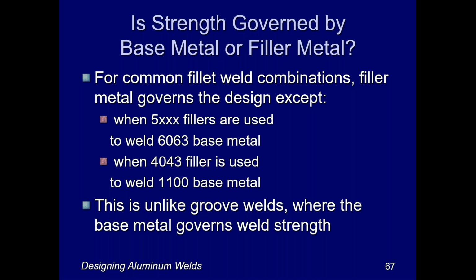And what that means is that you need to make the weld length appropriately long for the base metal. So when you have a case where the filler metal governs the design, you need to size the fillet weld and the length of the weld in order to match what your demand on that particular joint is. This is very much unlike groove welds, where the base metal strength governs the weld strength. So in groove welds, it's the opposite. You choose the filler metal so that it matches the base metal strength, the weaker of the two at the very least. And that's necessary in order to pass the qualification test for the procedure to make the weld.